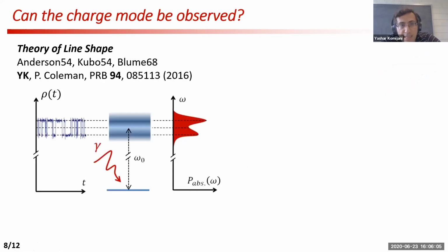Okay, so can this charge mode be seen in an actual experiment? Since the charge is fluctuating, if somehow we could bring a two-level system close to this fluctuating charge, it could be possible that we could probe it. For example, imagine a nuclear transition, and imagine that this nuclear transition is hyperfine coupled to this charge. Then the energy of the excited state is fluctuating together with the charge, and therefore, if I do spectroscopy on this nuclear transition, I will not see a single peak, but rather a two-peak structure.